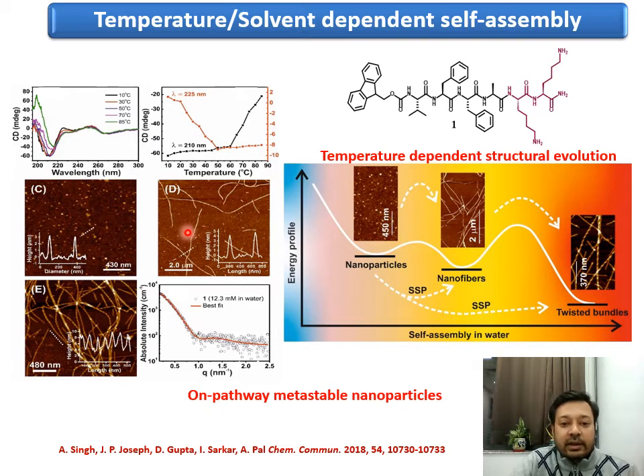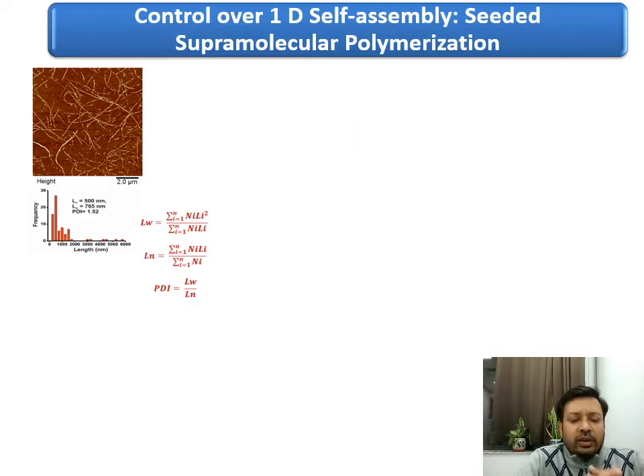These nanoparticles can get converted into kinetically controlled nanofibers, which on repeated annealing can form very nice twisted bundles. Now, these nanoparticles are on pathway because they immediately get converted to nanofibers. When we looked into the nanofibers, they are pretty much polydisperse in nature. We looked into the polydispersity index of the length distribution of these fibers, which is 1.52, which signifies that this is definitely not a thermodynamically controlled self-assembly, for which the PDI would otherwise have been more than 2.